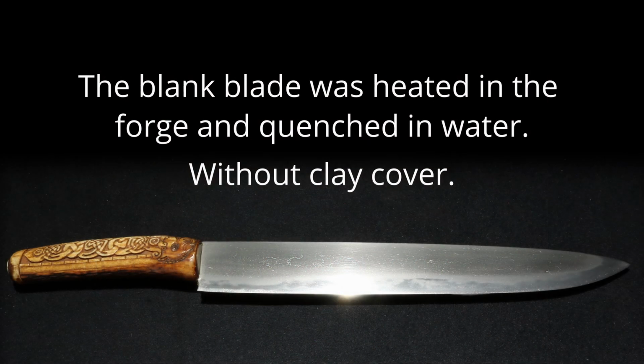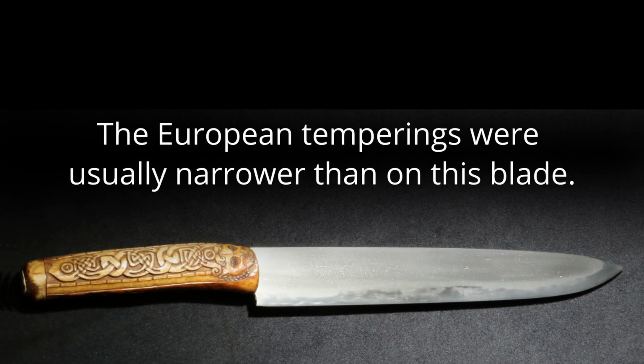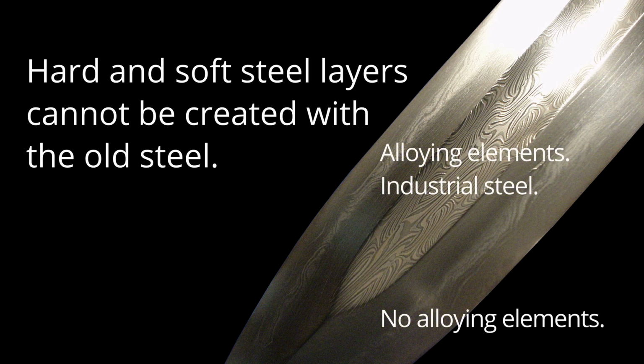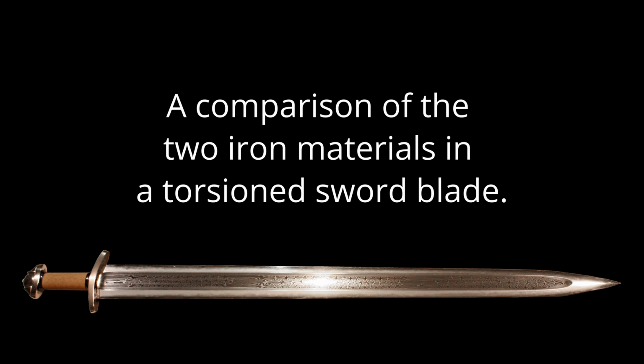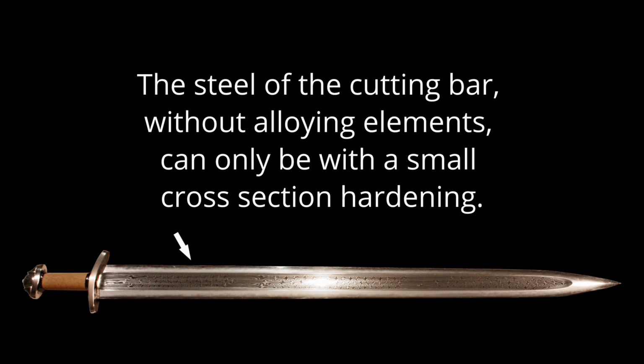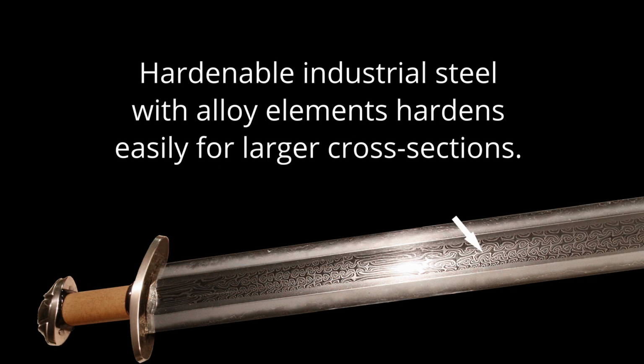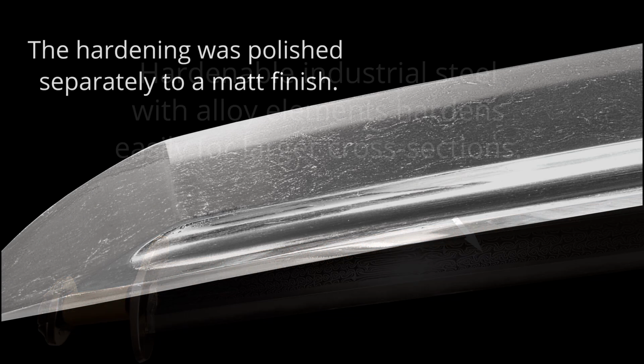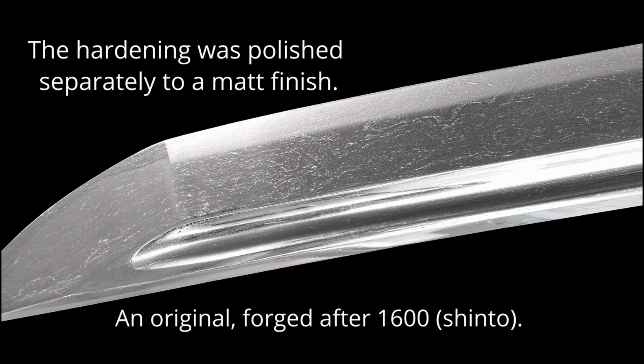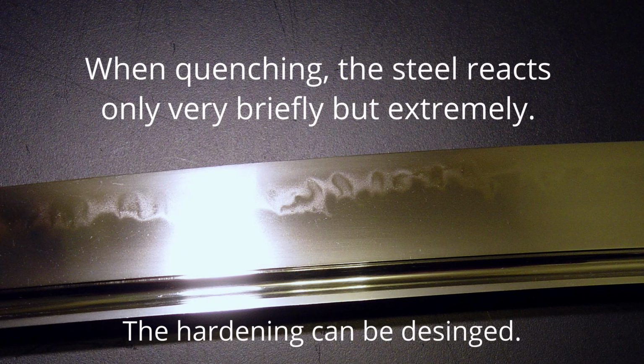The picture shows a blade I made decades ago, which shows the correct hardness ratios of European historic steels. This stepped hardening is the full hardening capacity of a steel that was not produced in the melt. The image in this steel is absolutely typical of historic steels: a grain consisting of oxide lines, and a stepped hardening along the cutting edge. It is obvious that this image of steel in no way corresponds to the composite of industrial steel, based on hardened and soft steel layers. The relationship to Japanese blades is absolutely obvious. No wonder. It is the same steel manufacturing process and it is the same steel. These connections are still practically unknown today.